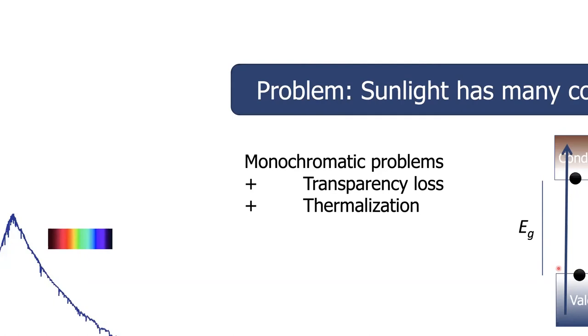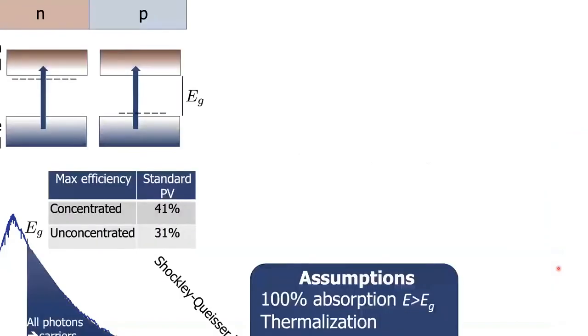When you put these three problems together, transparency, thermalization, and radiative emission, you end up with the most famous limit in solar energy, which is the Shockley-Queisser limit, worked out by Shockley and Queisser in the early 60s. And it says that if you have these rules, these optimistic assumptions, the maximum efficiency that you can get under concentrated sunlight is 41%, unconcentrated sunlight is 31%. Now, those are just the optimum, but it depends on what is the band gap of your material.